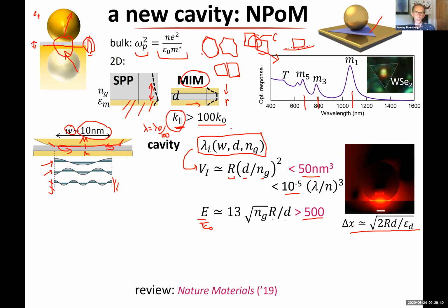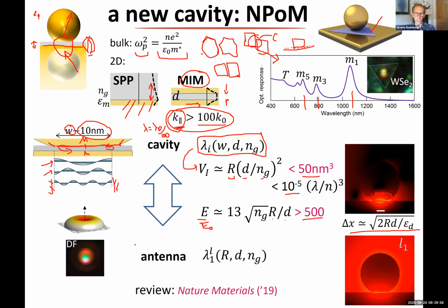The problem is that because this K here is so large, its coupling to free space is terrible. So if you just had this structure, say, a very small prism that sat on there, then actually it would be very poorly coupled to light. What's important is that there's also an antenna mode, which we called L1 here, which is a mode which looks like the mode over the whole of the dimer. And what you have to do is arrange for that antenna mode, which again you can write down analytically, to couple to that cavity mode. And when you do that, it's basically like impedance matching. The light will first couple into this mode and then it will couple into this mode, or they're really sort of mixed together. So you can see this paper for a review.